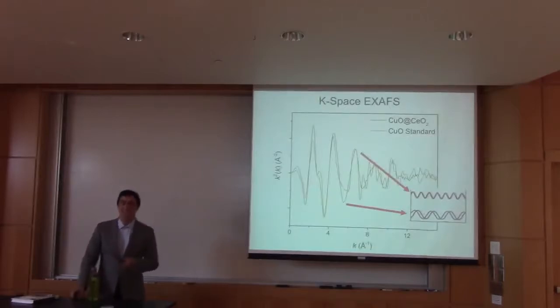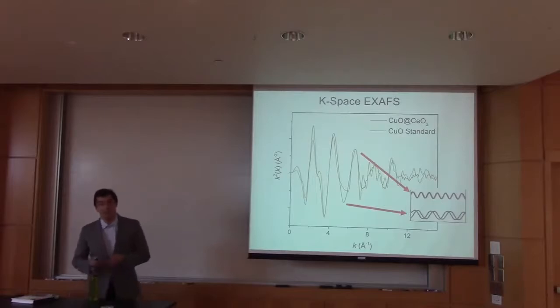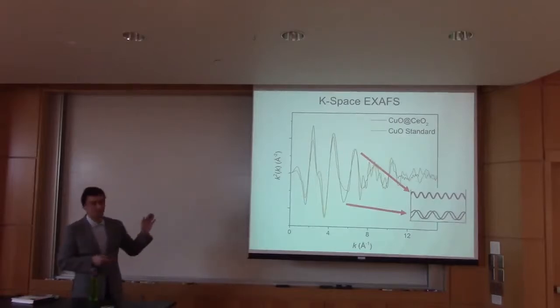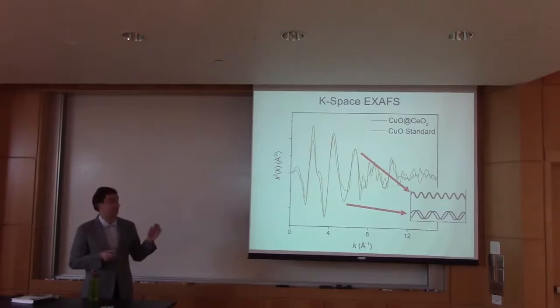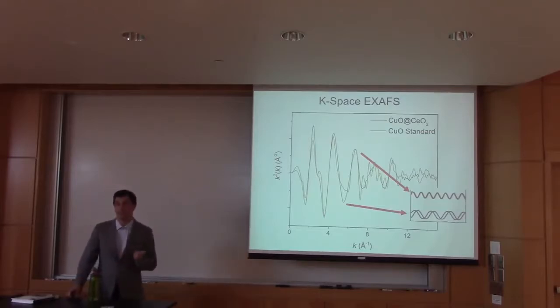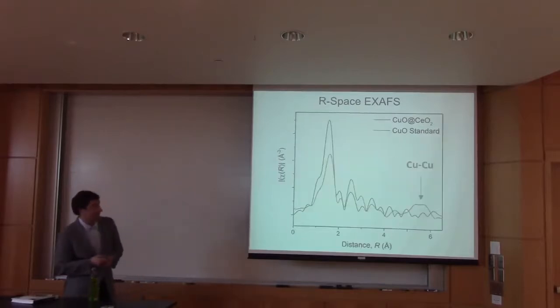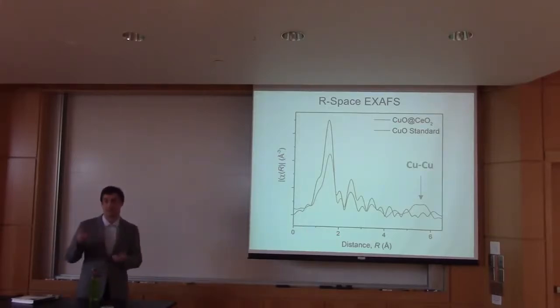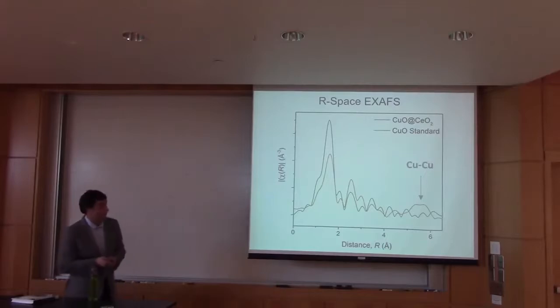And to do that, we need to take a Fourier transform of this data to obtain R-space data. In this Fourier transform, we're taking the component sinusoidal, so sine and cosine functions, and adding them together. And we're going to be looking at a function of energy plotted against distance and obtain meaningful data. So this is that R-space data where we're still looking at our catalyst sample and comparing it to a standard. We're looking at some function of energy plotted against distance. And this distance represents the distance from the absorbing atom to its neighbors.